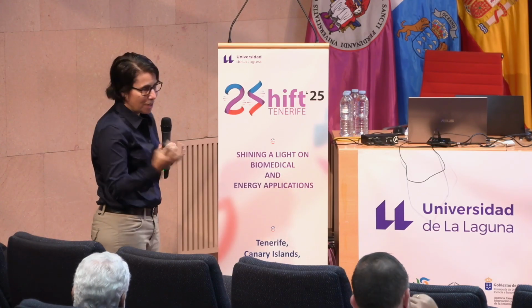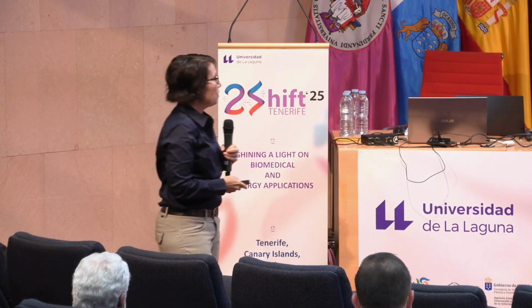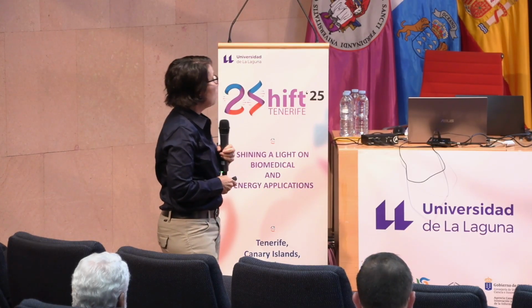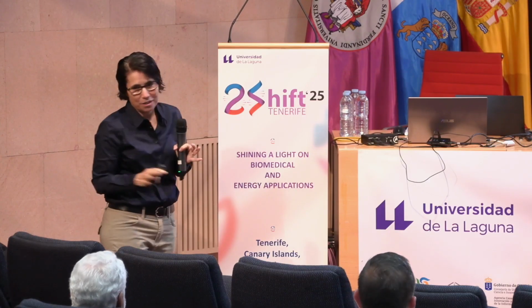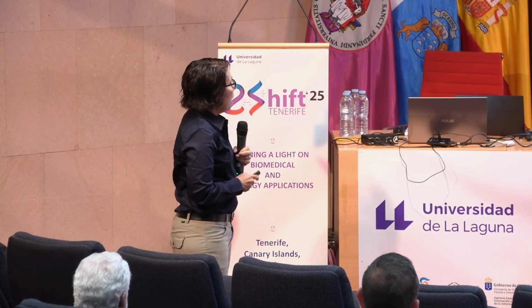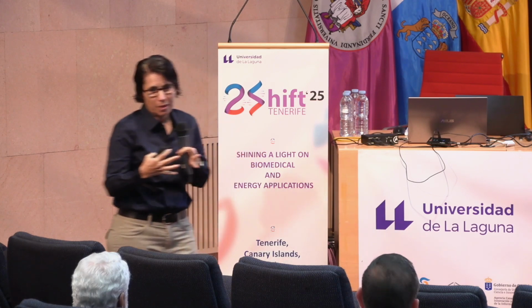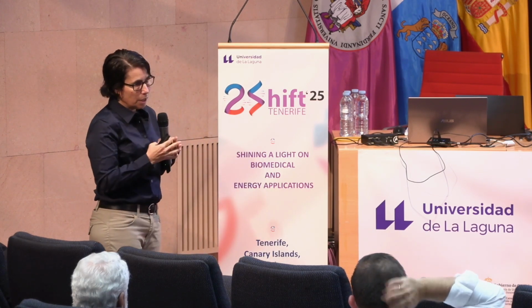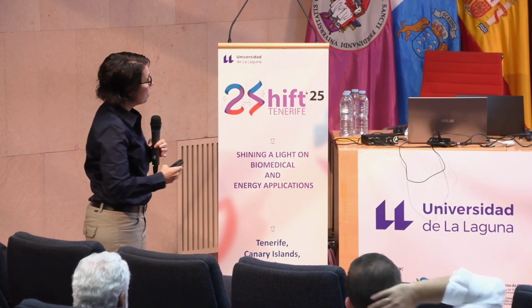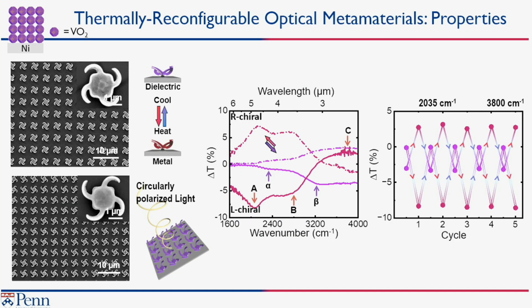So this is an example of these same kind of folding structures, but now they're made out of the phase transition material. And so if you look at it again, we can make left and right-hand enantiomers of these materials. And so what would you expect? So we built this system in our spectroscopy where we could heat this material through the phase transition temperature. So again, it looks like these structures are on a surface. At low temperature, they're in the dielectric phase, right? They're insulators. And so if you look now, we're looking out at long wavelengths. Remember that VO2, like we heard earlier, becomes plasmonic at longer wavelengths, past around 1.5 microns.